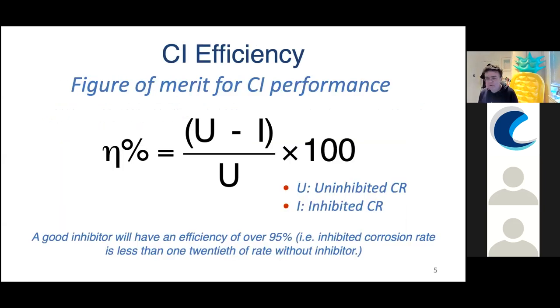An important aspect of corrosion inhibitors, of course, is how well they perform, how much they reduce the corrosion rate. And a particularly widely used figure of merit for measuring this performance is inhibition efficiency. It's given by this equation here, where U is the uninhibited corrosion rate and I is the inhibited corrosion rate, all divided by U, multiplied by 100 to get a percentage, and you want it to get as close to 100% as possible to be as effective a corrosion inhibitor as possible. And typically, it's considered that an efficiency over 95% would say that the corrosion inhibitor is working well. This is a somewhat artificial level, but that's typically accepted in many areas. And so in that case, the corrosion rate will be 1/20th of the rate without the inhibitor. And we'll come back and use that later on.